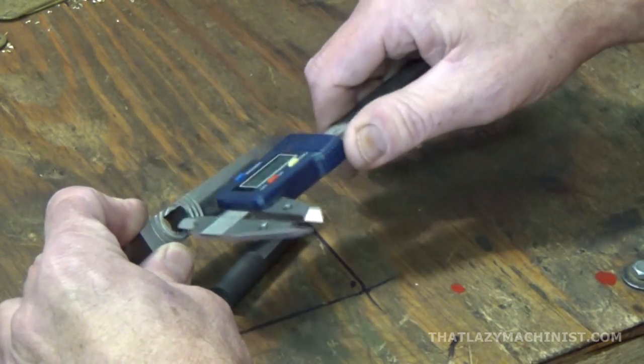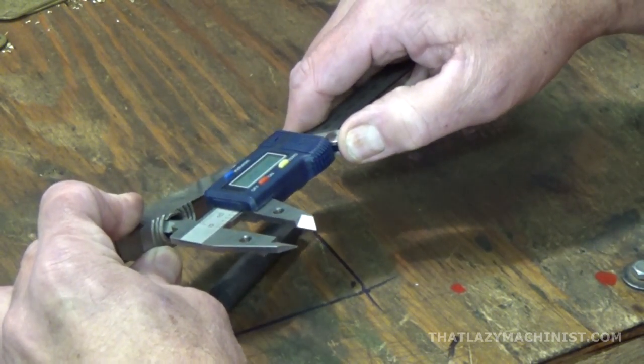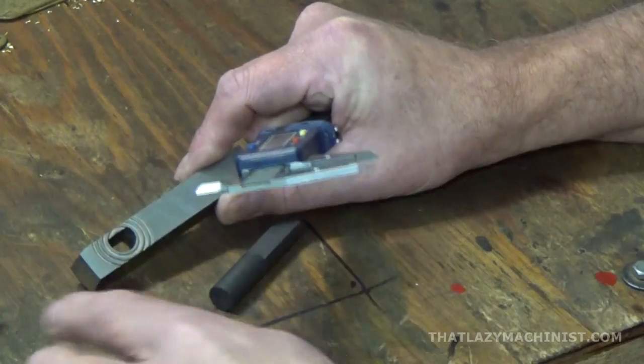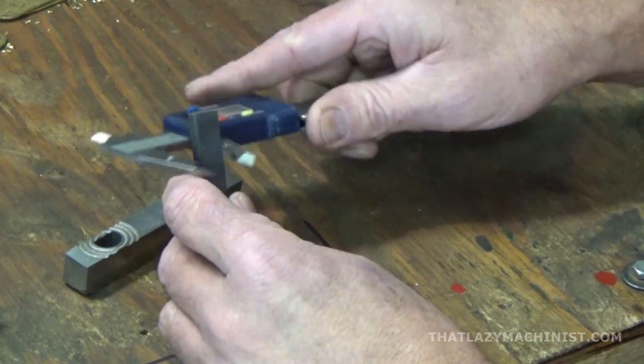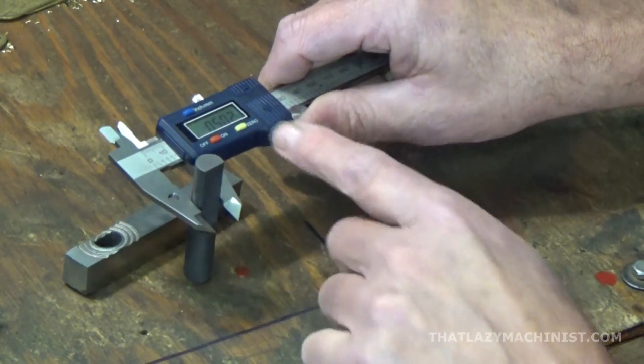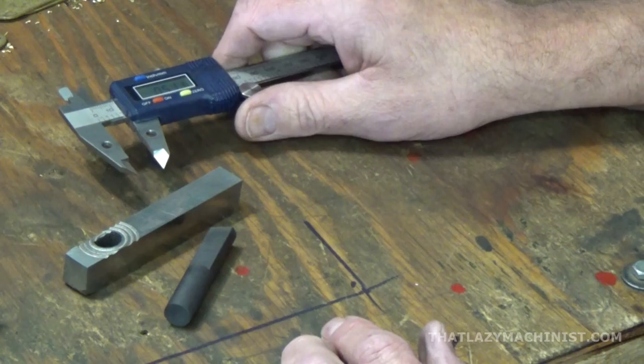So let's, to answer those questions, start by measuring the cavity or hole that we produced and our electrode. If I measure the D hole that I produced, it comes in at 515 thousandths of an inch at the top here, where we started to produce the hole. And if I measure my electrode, where it hasn't come in contact with the part, well, I have 502 thousandths of an inch.